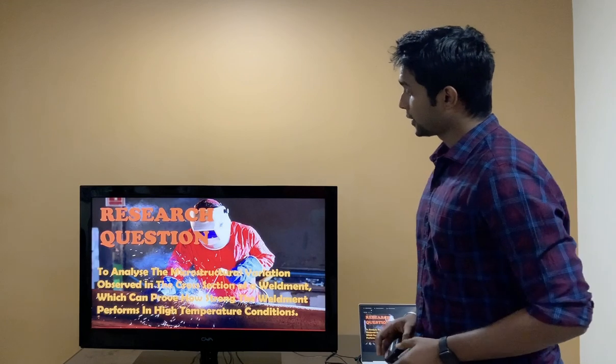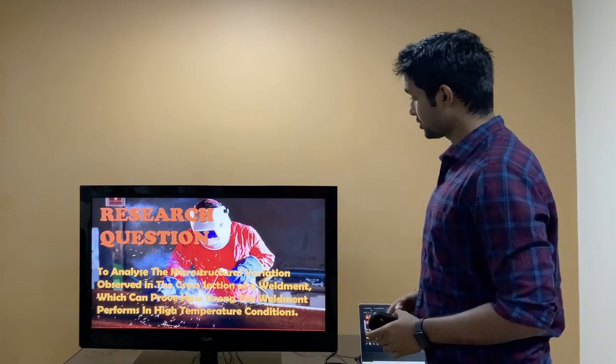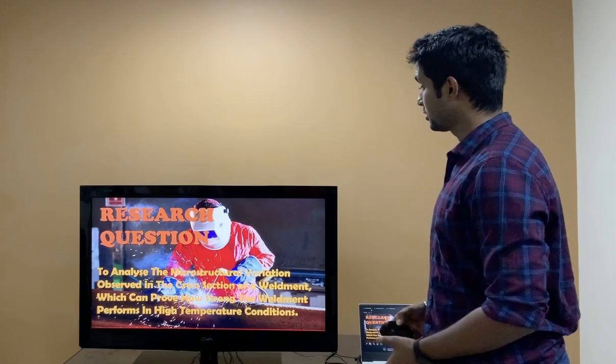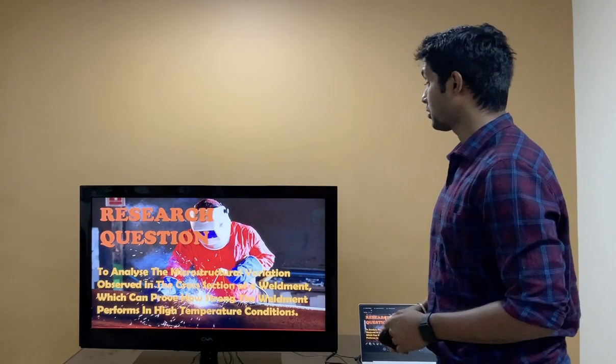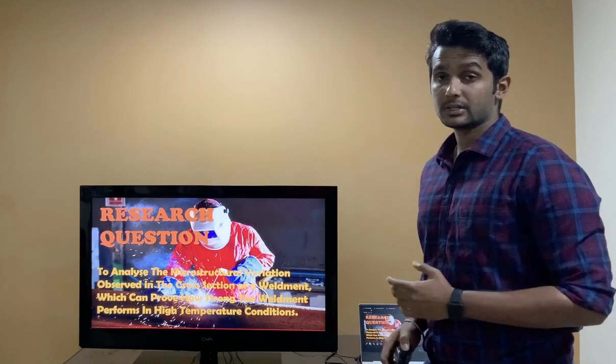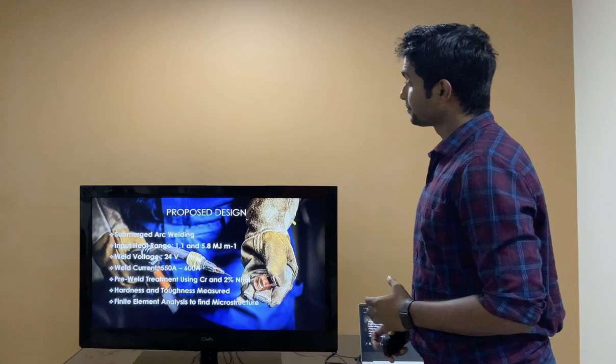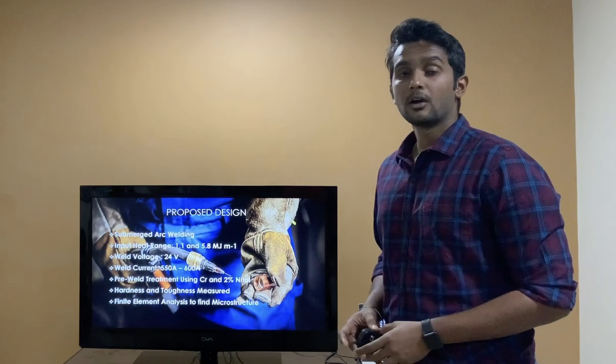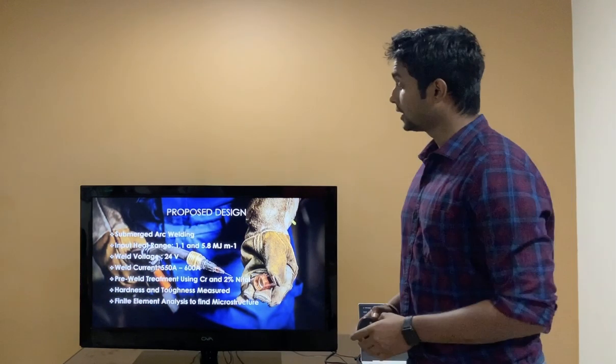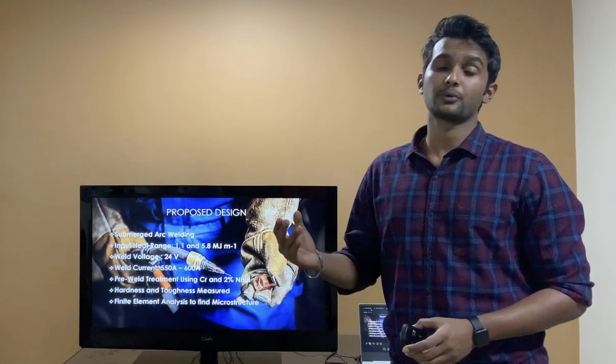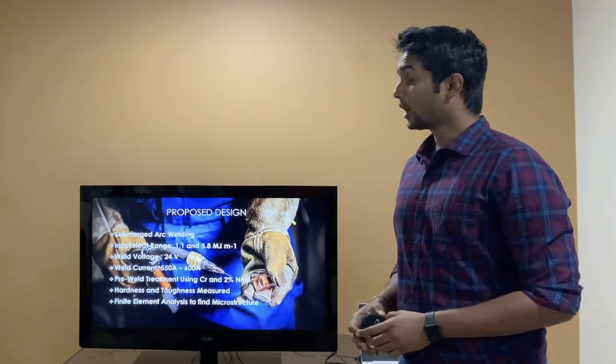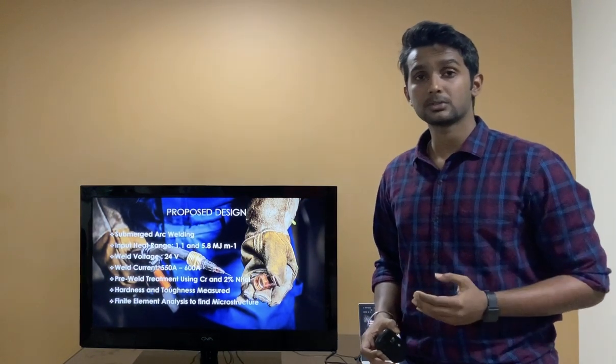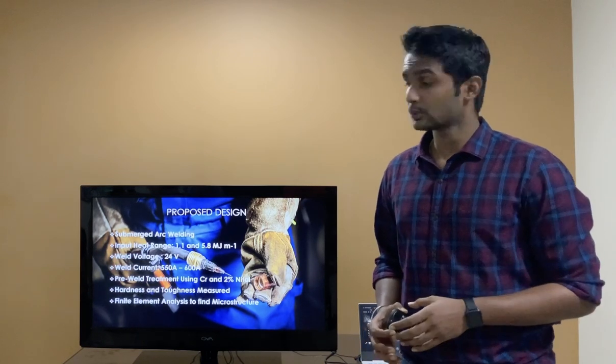And here comes our research question. That's to analyze the microstructure variation observed in the cross-section of a weldment, which can prove how strongly the weldment performs in a high temperature condition. So here is our proposed design. For this design, I've chosen submerged arc welding due to an array of reasons: it would produce less fumes, and it would consume less weld metal as well.